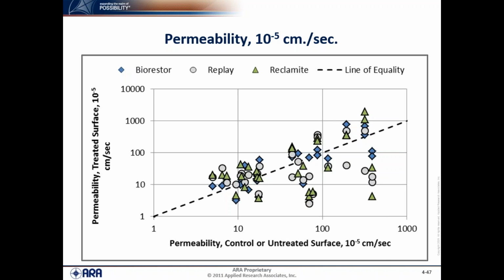They're generally, and initially, along the line of equality. Over time, because this is the last set of field permeability tests, you can start to see that some of the treated sections have maybe consistently a lower field permeability than the control, but we can't really say statistically it's a lower number because of the variability in the data.